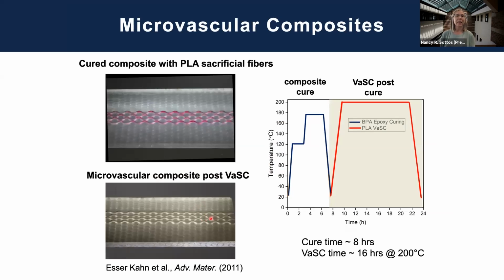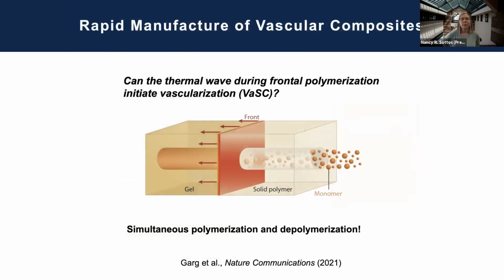All right? And it has some limitations, as you can imagine, as you're trying to get something to go through a cure cycle like that. So as we got started with our frontal polymerization process, we asked this question: can the thermal wave during frontal polymerization, we've got a lot of energy there, sometimes quite a bit of excess energy depending on the monomer and the boundary conditions, but can that initiate vascularization? Can you have simultaneous polymerization and depolymerization, polymerization of the monomer and depolymerization of the sacrificial template?